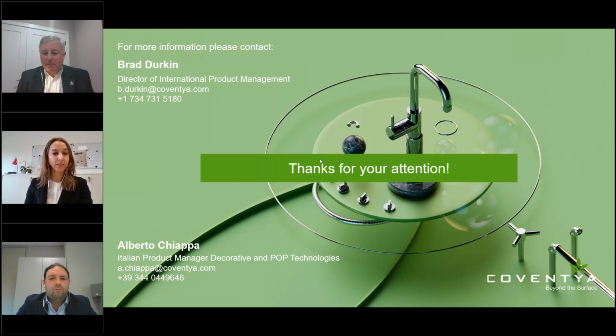The result after 480 hours of neutral salt spray test was very good. And is it also possible to attain this result with the decorative aspect of the Tristar 330 AF and with the blue-toned color of minus, very negative value of B? Yeah, the performance remains stable in time. For this reason, the aspect after 480 hours of salt spray is a good result, because it maintains the color and the stable performance of the corrosion. Okay.